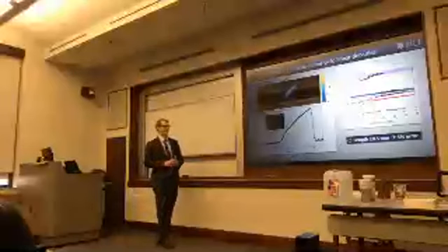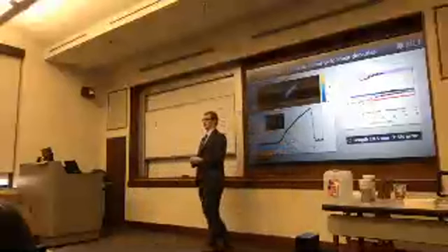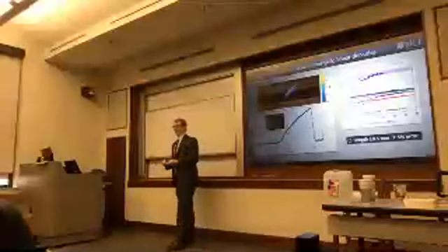Yeah. Sure. Okay, so the last thing I want to point out about this is that although it does seem to work, it's very sensitive to the gauge length that you set. So if you're off by 0.5 millimeter in the length, that results in about 5% error. And 0.5 millimeter is actually really hard to control experimentally. So that's definitely something that has to be considered as we continue to analyze data with this method.